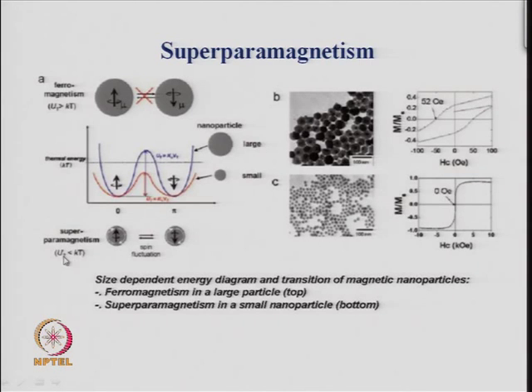So, whenever the energy required, this value is called U, and whenever it is less than kT, where kT is the thermal energy, then you can have spin fluctuation and then it will result in superparamagnetism.